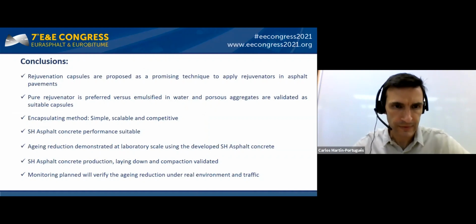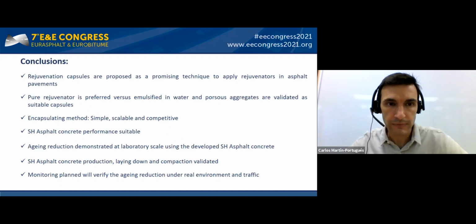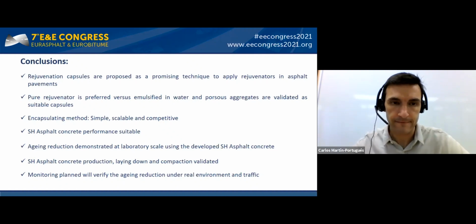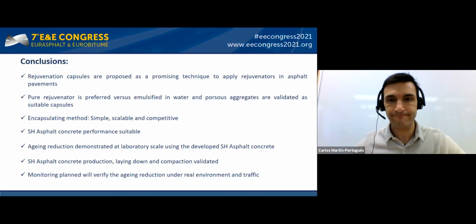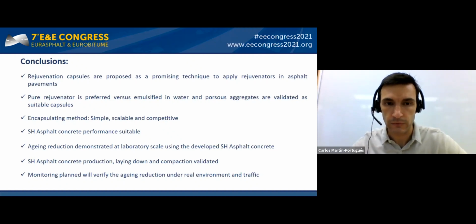So, conclusions. The technology developed in terms of encapsulation is promising, and the technology was validated, and the pure rejuvenator was confirmed as a better result compared with the emulsified one. The encapsulate method is simple, is scalable, and is competitive, as we demonstrated. The self-healing asphalt concrete performs feasibly and, according to the quality control, accomplished the regulation.